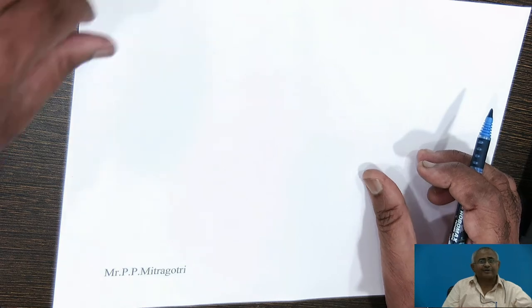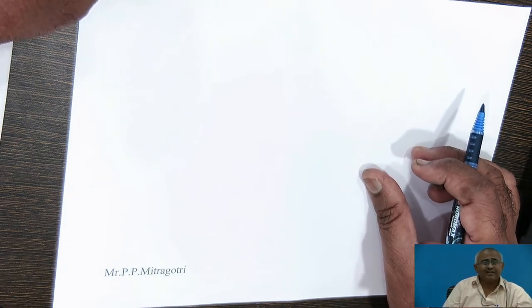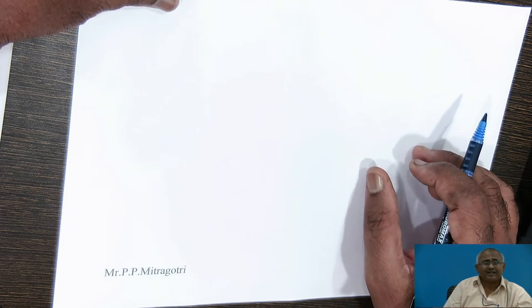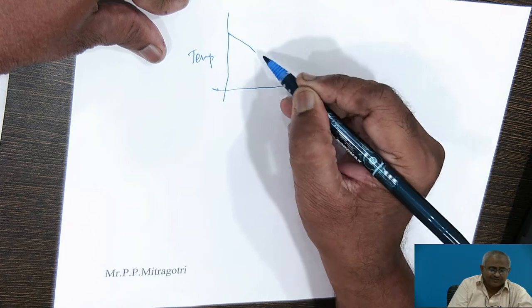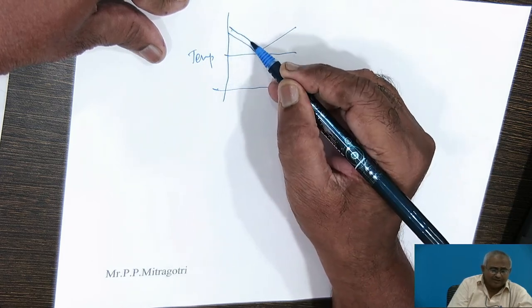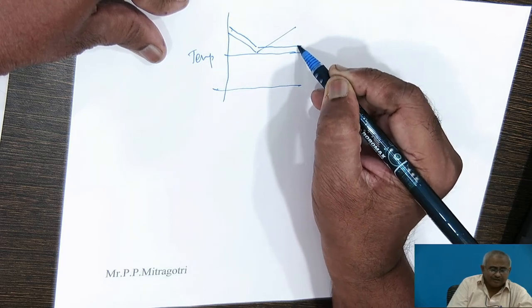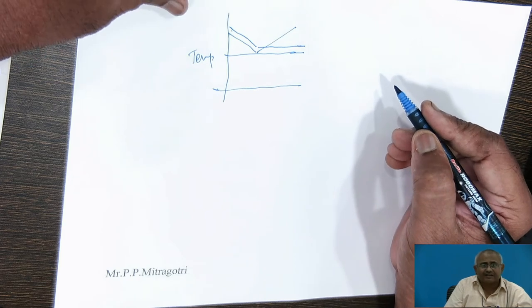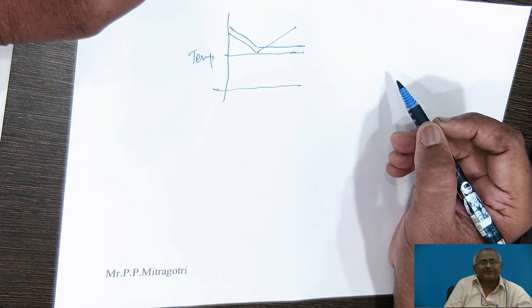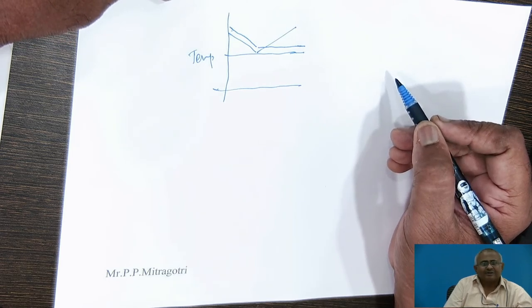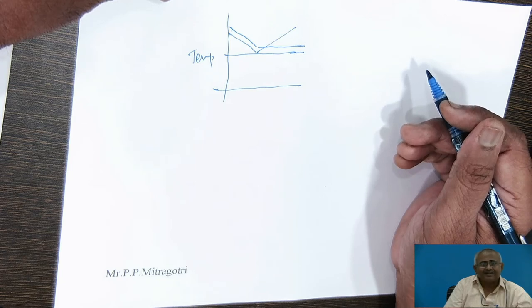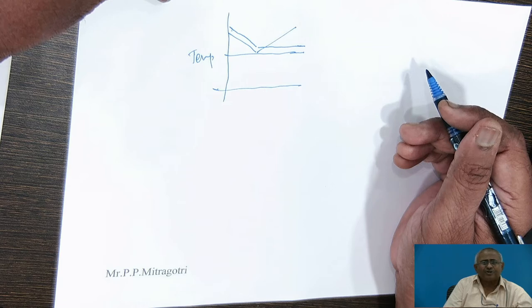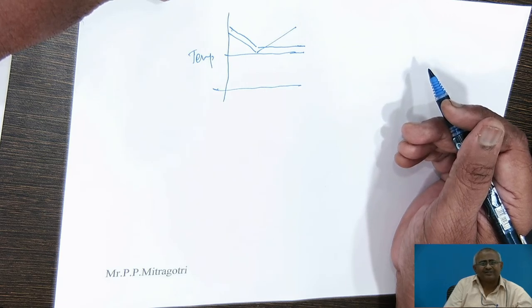As already stated, austenite is transformed to martensite. What is the temperature range for heating steel for hardening? We generally heat hypo-eutectoid steel 40 to 50 degrees above the A3 temperature. You may ask why hyper-eutectoid steel is not heated above the A3 temperature. The answer is simple: above the A1 temperature in hyper-eutectoid steel, we have austenite and cementite. Cementite is equally as hard as martensite, so there is no point in wasting time by heating the steel above A3.